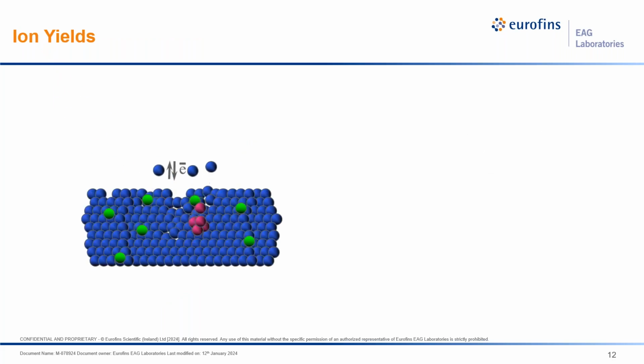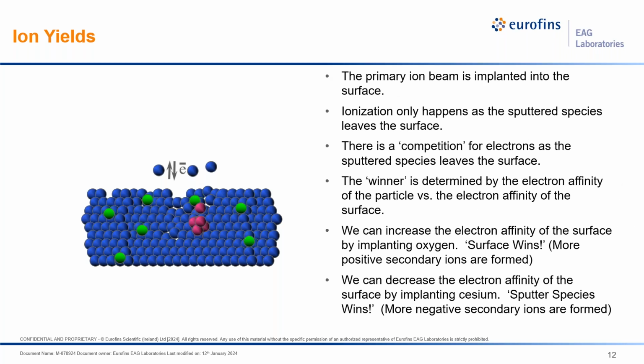So, ion yields. What is happening during the sputtering process? The cartoon shows that the primary ion implants itself into the surface, ejecting some material from the material, but also leaving behind what you implant. The ionization only happens as a sputtered species leaves the surface.